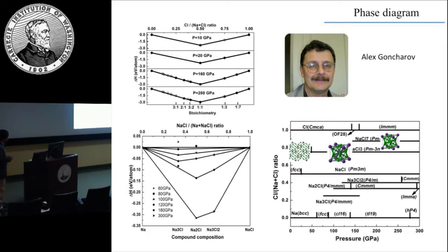So the way to read this, if you're not familiar with that, this is called a Hull figure. It's a plot of energy versus stoichiometry. Anything far below a straight line is a stable phase. For instance, if you look at sodium and chlorine, sodium chloride is below this line, which means it's more stable than sodium plus chlorine combined. Then at low pressure, indeed, that's the only stable phase. But increasing pressure, you start to see that those lines start to curve. That means if you draw a straight line between sodium chloride and chlorine, you will see this phase below the line. So here, sodium chloride and sodium, then you exaggerate the vertical scale, you see those below that. So the theoretical calculation means that anything below that is a stable phase. Okay.